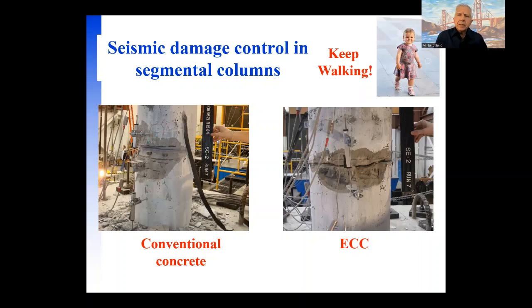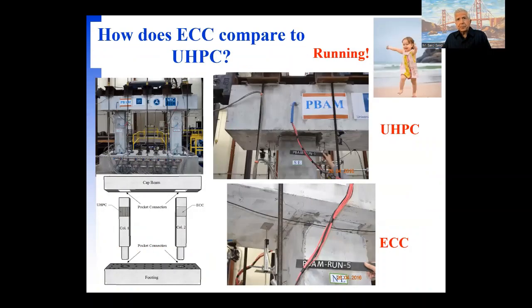We kept walking by saying, okay, well, what if we use ECC in segmental columns and in other, again, seismic loads, because this is the kind which is attractive for accelerated bridge construction. So here you notice a conventional concrete that was used in a segmental column versus ECC. Again, you see quite a bit of damage in the conventional column, but the damage in the one in which we use ECC in the segments was a lot less and certainly controlled and easier to repair.